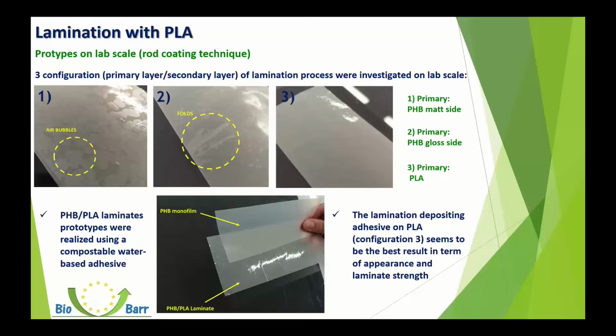Another technique that is widely used for the functionalization in converting is the lamination with another polymer. For PHB, obviously, the other polymer also needs to be compostable. So we decided to perform the lamination with the PLA. We realized prototypes of PHB PLA laminates using a compostable water-based adhesive by rod coating techniques.